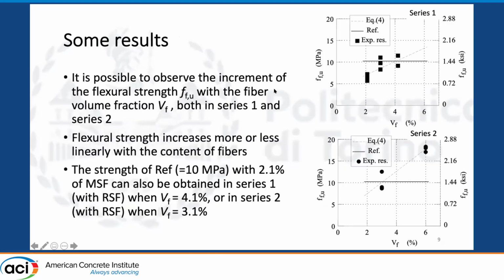So I just comment some results, in particular from the flexural test, we obtained the flexural strength. And both in the case of series 1 and series 2, the flexural strength increases linearly with the content of fibers. As you can see, these squares are the test results. Then you have the trend line here, and in these circles are the results of series number 2, and of course this is the linear trend that we have.